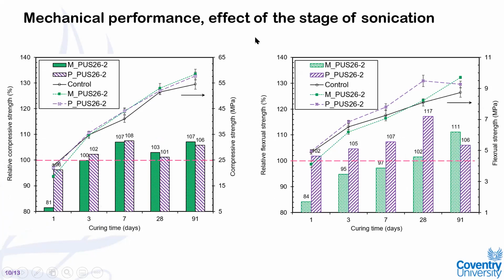And we studied the effect of the stage of sonication by applying sonication to the mortar at once, the green bars, and the hatching bars denote the result of sonication of paste before addition of aggregate to make mortar. As you can see, the improvement in the compressive strength and flexural strength of samples when the paste is sonicated before addition of aggregate is evident in these graphs. And even at a later age, you can see the improvement in flexural strength, specifically in flexural strength of samples, due to the application of 26 kilohertz, even for only 2 minutes.